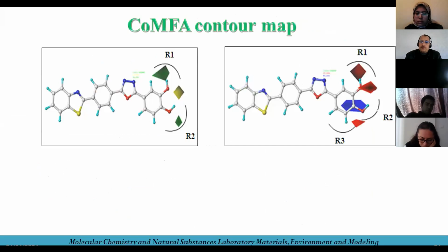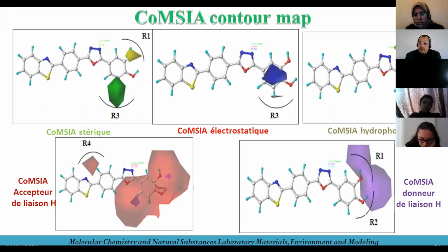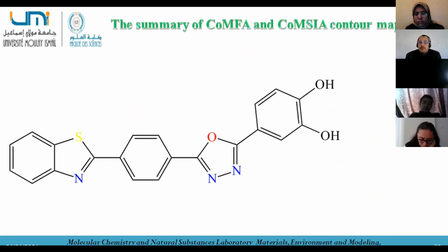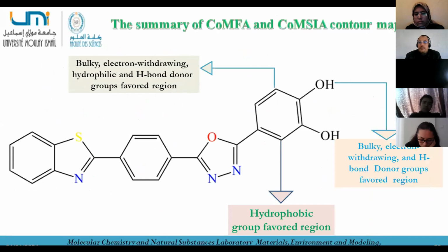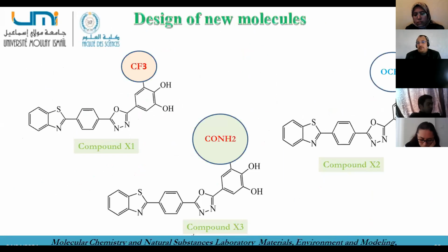The following figure shows the contour maps of CoMFA, steric and electrostatic. From this figure, we notice that the green contour shows where bulky groups are favorable, unlike the yellow contour. The blue contour shows that the substitution of electron donating groups increases activity, unlike the red contour. The same explanation applies to CoMSIA. So, based on all these contour maps, we proposed and designed three new molecules with more important activity than those of existing molecules.